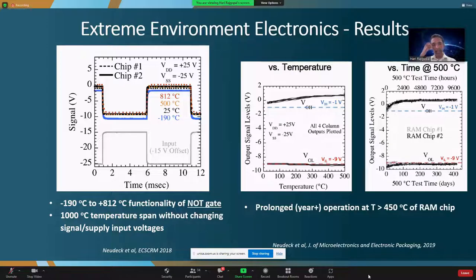And so these are the results. On the left, you'll see a very simple NOT gate, but what is pretty amazing to me, because this predated my joining NASA, is that our group has demonstrated electronics over a 1,000 degrees centigrade temperature span, from minus 190 to 812 degrees C. What is the relevance of the minus 190? That is how cold the coldest region of the moon gets, about minus 190 C. So we are trying to demonstrate that this is not just useful for Venus, it could also be used for the moon.